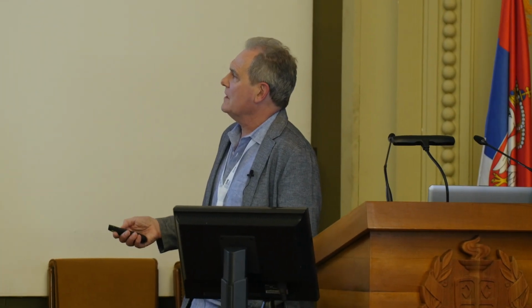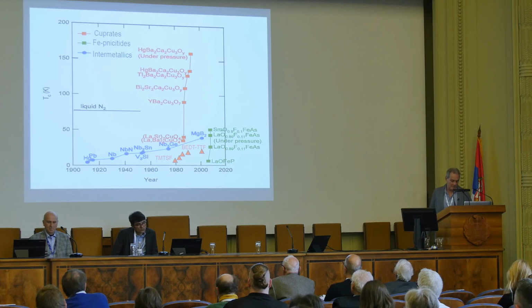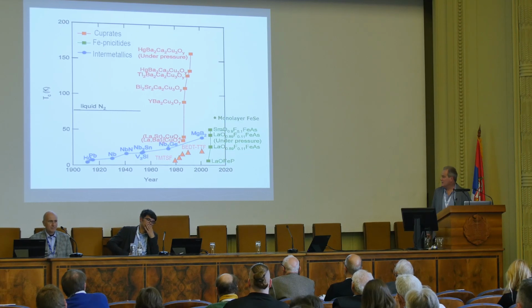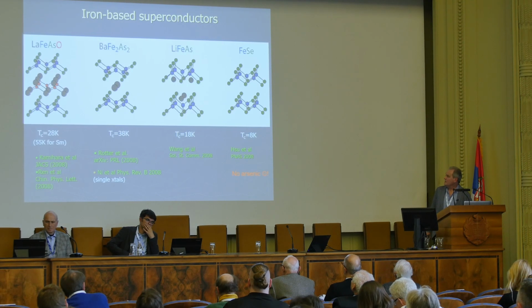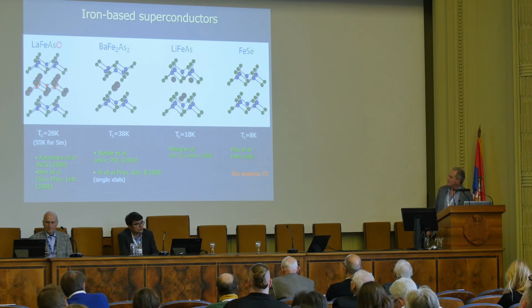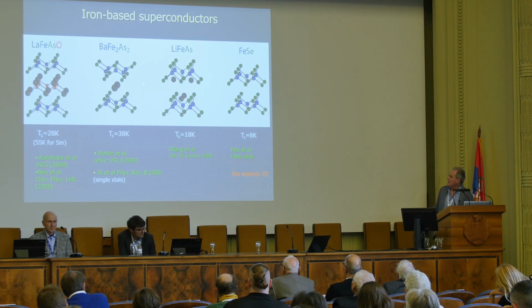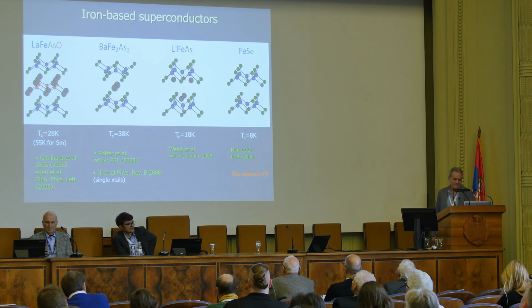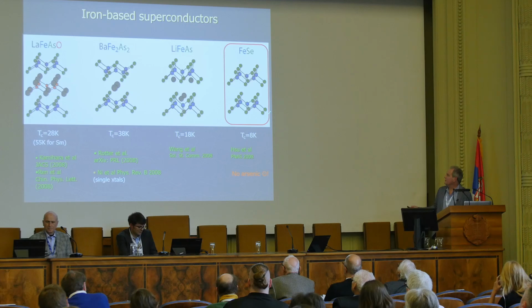And so we add these new materials to our TC versus year diagram. The critical temperature went up again very rapidly in terms of discoveries to about 55 Kelvin, and then shortly thereafter with monolayer iron selenium to about 70 Kelvin. And there it has stopped until now, I would say. These materials also have a common square lattice, not of copper and oxygen this time, but of iron and a pnictogen or a chalcogen. And then again, spacer layers to dope those planes. They range from a few Kelvin up to 70, as I said. Iron selenium is the simplest one. It's just one iron selenium plane.